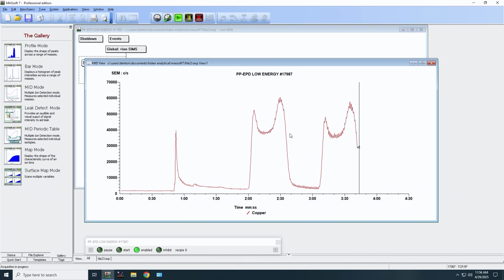You can also run oxygen through the source itself, and you can see the signal goes up. It depends on the material and your etch conditions, but it can go up 2x or it can go up 10x. So that's one method where you can enhance the SIMS signal if you have a very small chip, or a material that's a very thin layer, or there's not very much of it, and you want to enhance the signal. You can try adding oxygen through the source itself.